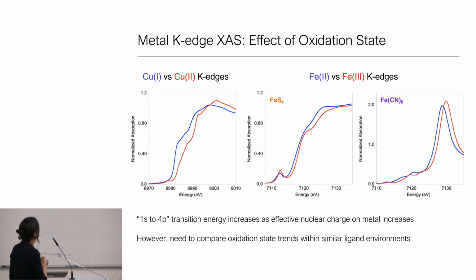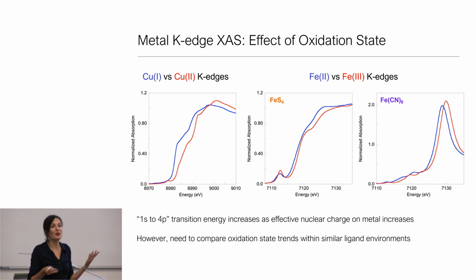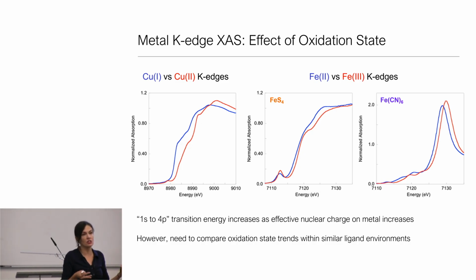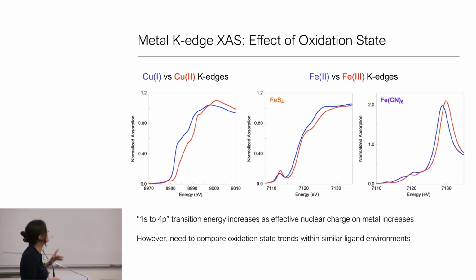And so what I'm showing here on the left at just below 9,000 electron volts are copper K edges of a copper 1 in blue and a copper 2 in red. And so what you can clearly see is that when we're more oxidized, it takes more energy because we have a higher effective nuclear charge to actually ionize the 1s electron, and the edge shifts up. So that's a simple metric that these edges reflect something about oxidation state.